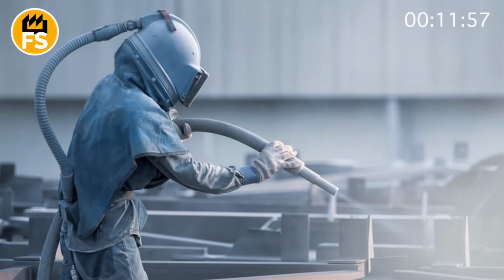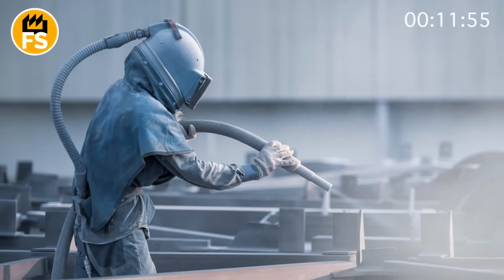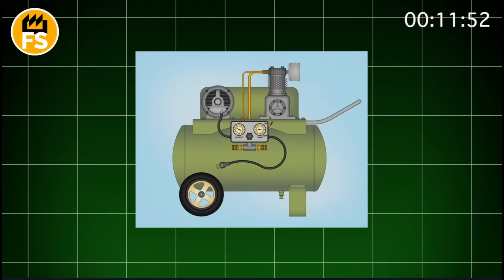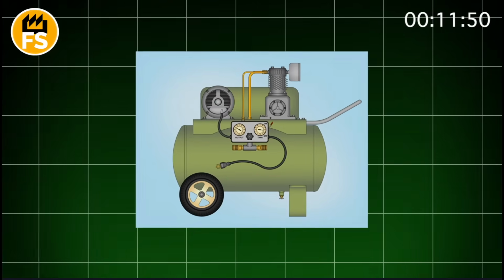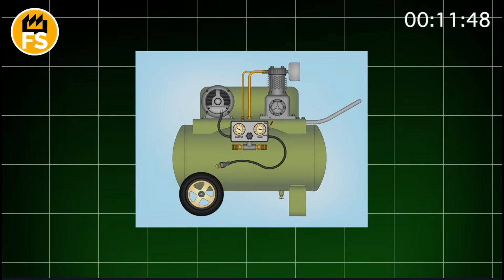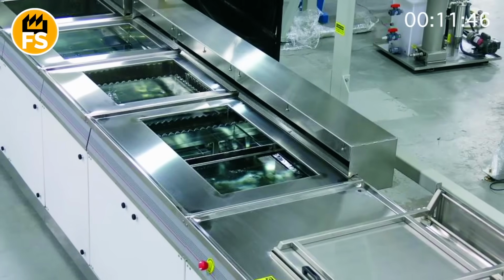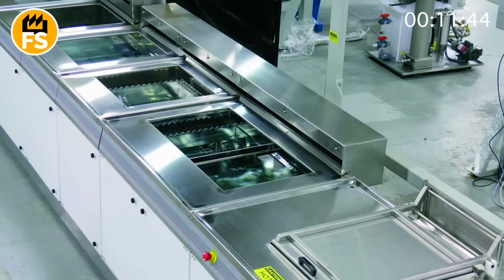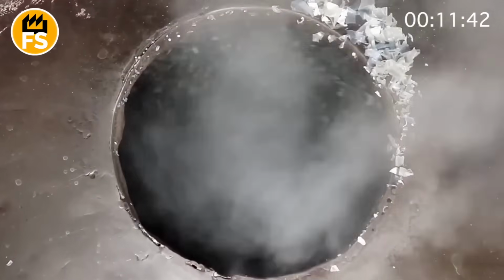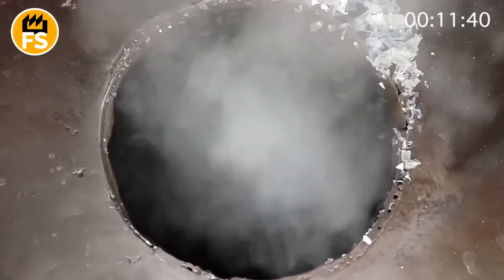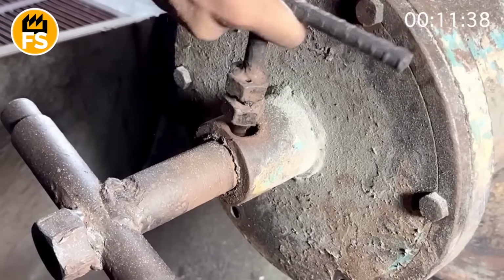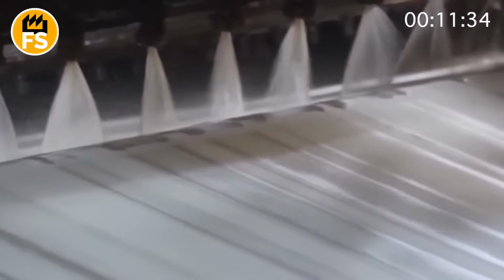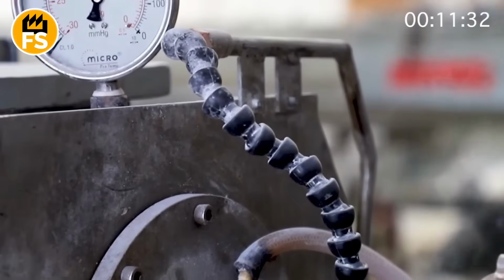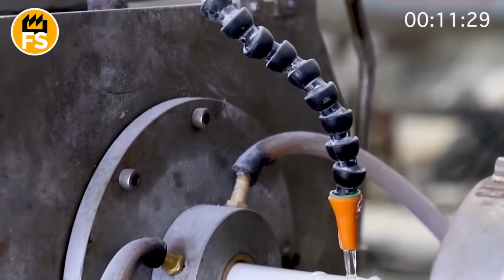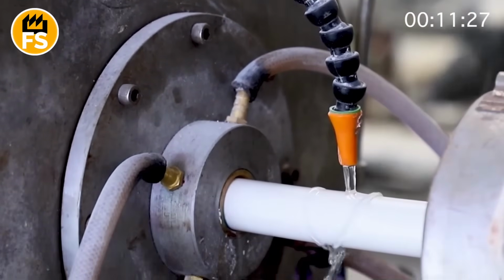The spool is brought inside on a special platform. Then, the roar of a compressor and a stream of fine abrasive starts hitting the steel surface under high pressure. Sometimes quartz sand, sometimes steel balls. It sounds like a storm of hail hitting tin. The surface changes before your eyes. Where there was just dark mottling, now there is an even, matte gray metal with a slight roughness. If you run your finger over it, you feel not smooth, but slightly velvety to the touch.